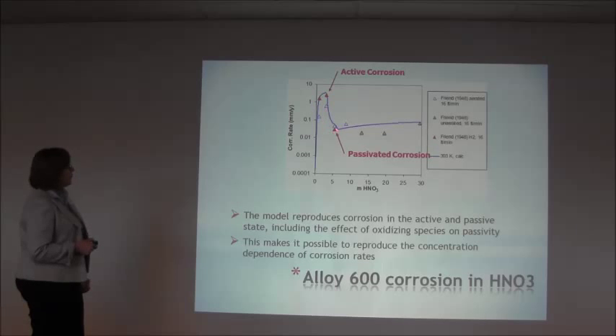And this is a typical corrosion rate calculation. What we're looking at is a passivating film. As more nitric acid forms, we're moving into a passive state. So the corrosion rate gets high, and then drops and becomes low.